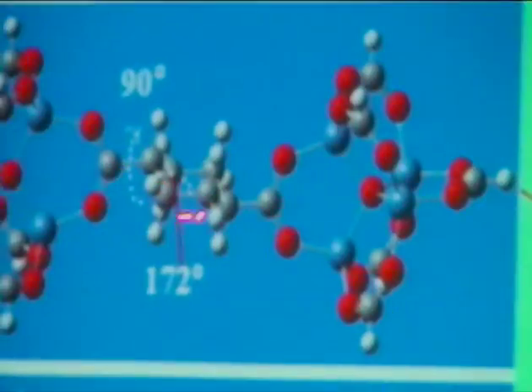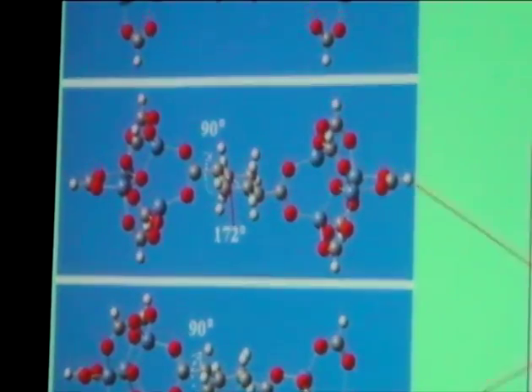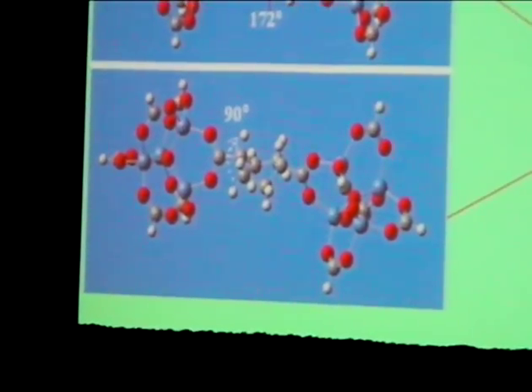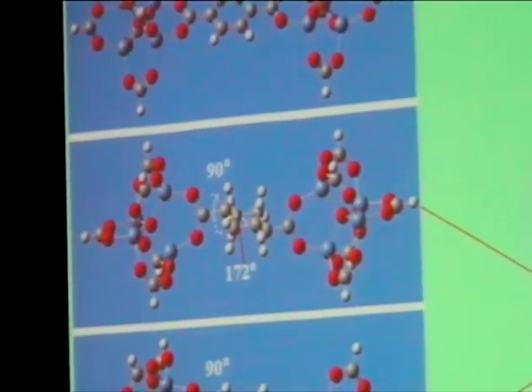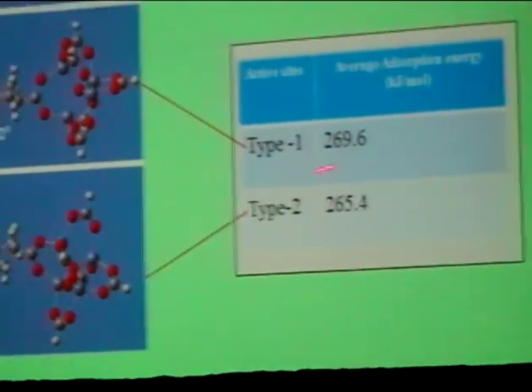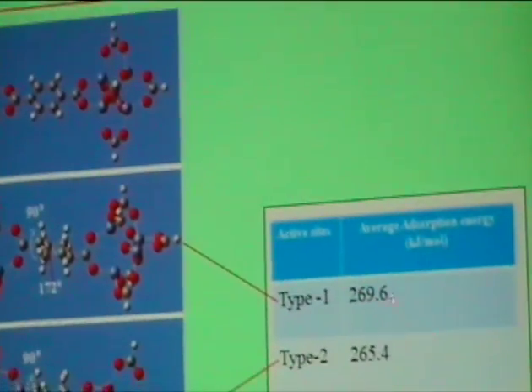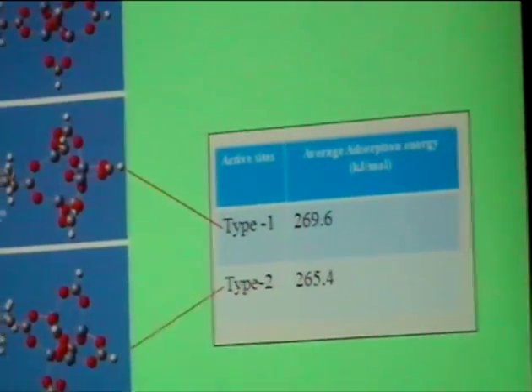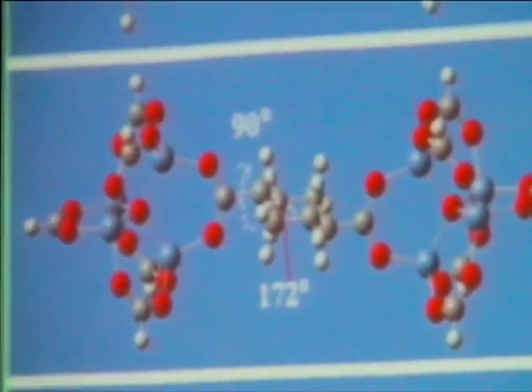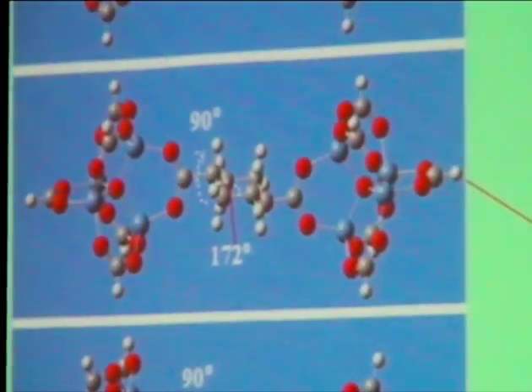But if we use 6 hydrogens to saturate the 6-membered ring, you can see that the interaction is stronger. The reason is that if you break 1 double bond, you need 2 hydrogens. So if you break all the double bonds, then you need 6 hydrogens. If you put all 6 hydrogens on, you get an even stronger interaction, so that makes sense. You can see the active sites interacting with hydrogen can form a very strong interaction, 269 kilojoules per mole interaction energy. These are two structures, one like an armchair and another like a bird. You can use both structures to get high interactions.